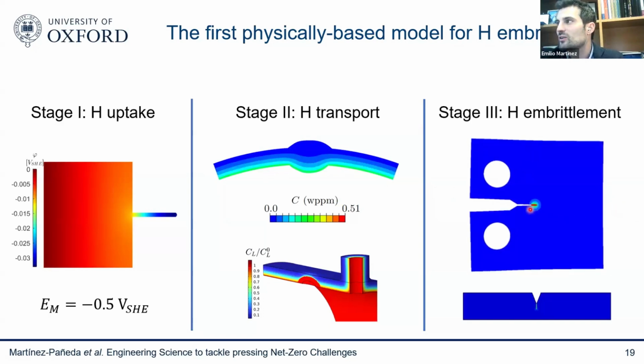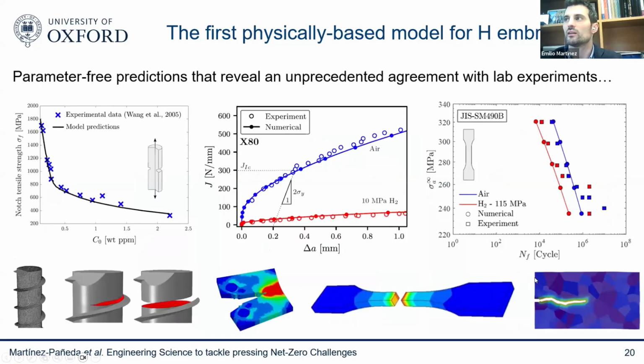So here in red, this is a crack. You can see this is what we call a compact tension sample. We're applying a load, and you can see that the crack is growing. This is a cyclic load. This is fatigue loading. You can see that the crack is growing, accelerated by the presence of hydrogen. This is another geometry. And any geometry that you're interested in, you can simulate it. And these models have proven to work out very well.